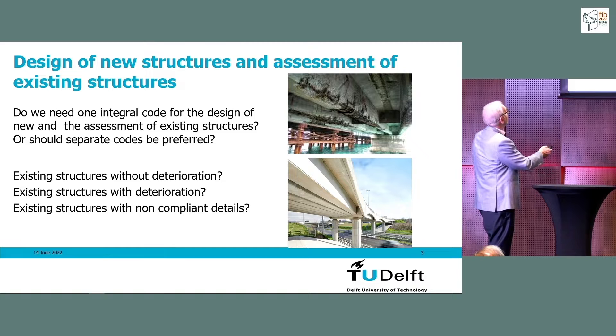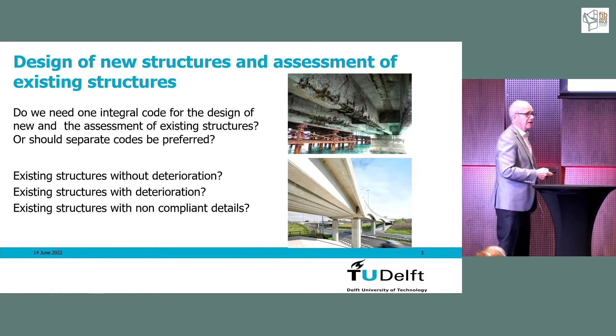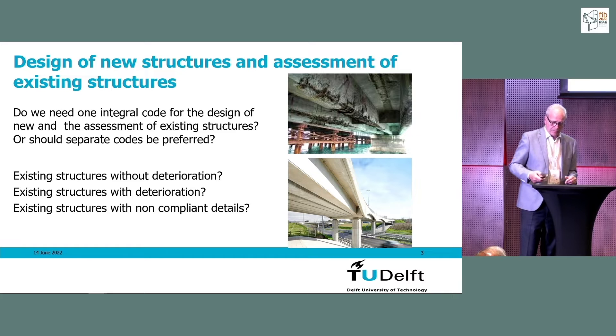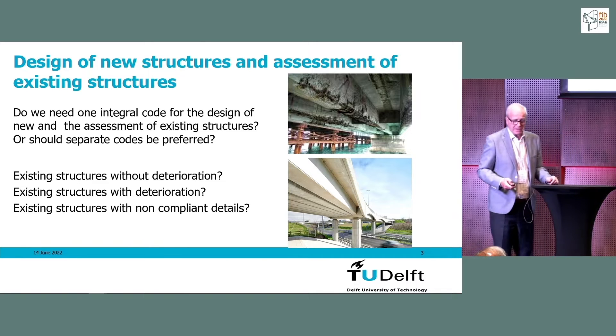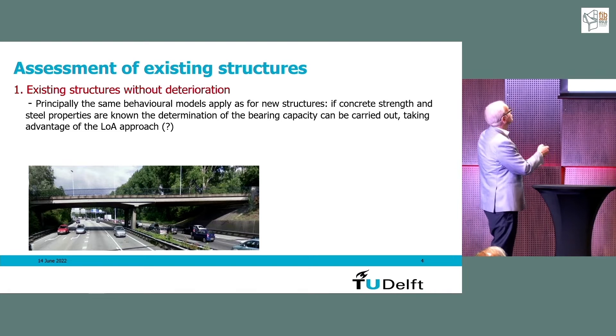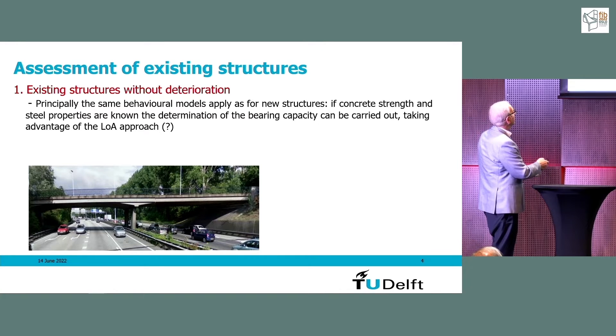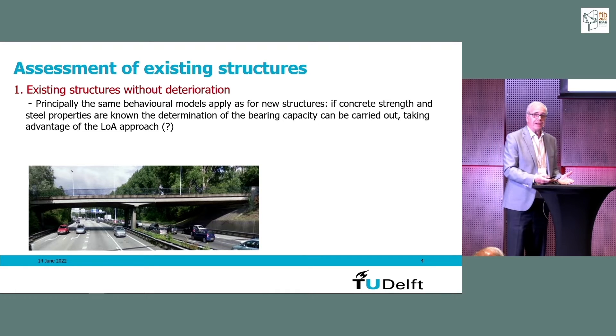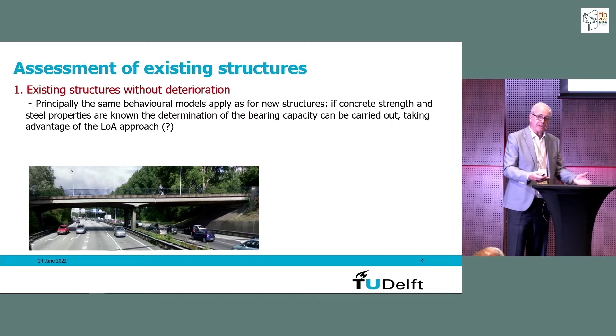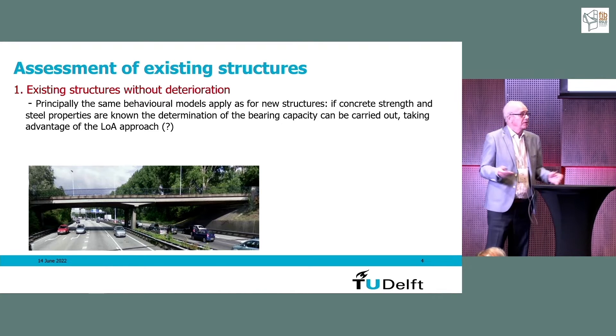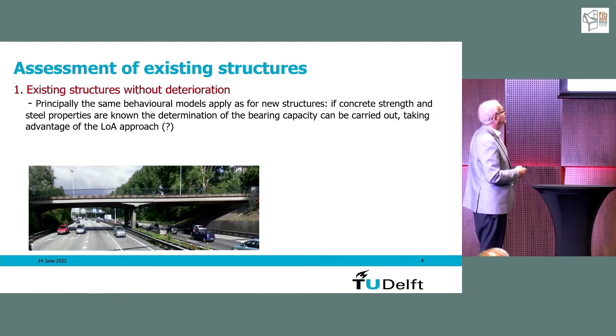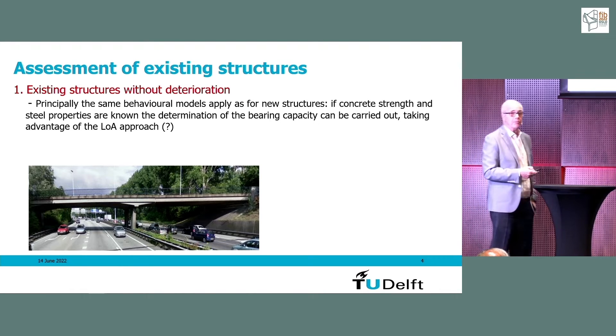We have three questions: what to do with existing structures without deterioration, with deterioration, and with non-conforming details. In the Netherlands, we had many solid slab bridges. An early analysis based on simplified design capacity checks suggested many should be unsafe, but we were not sure, so cylinders were drilled from the top and bottom of several solid slab viaducts.